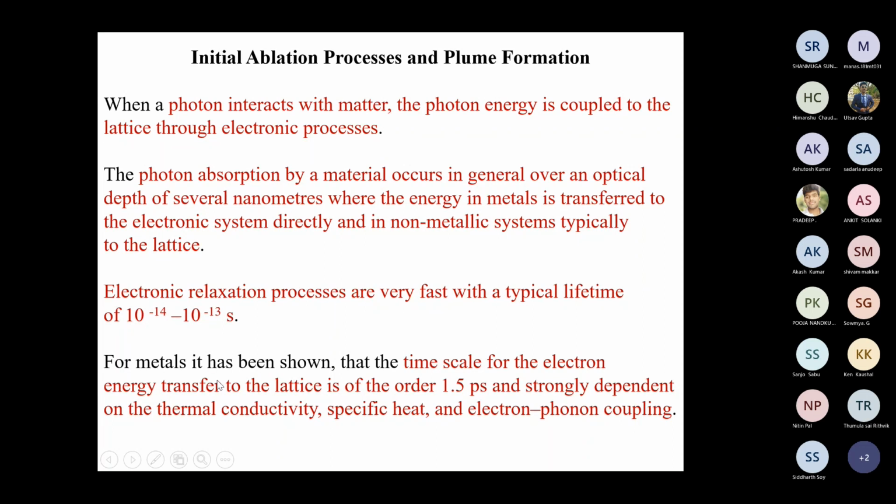For a metal, it has been shown that the time scale for electronic energy transfer to the lattice is on the order of 1.5 picoseconds, and strongly depends on thermal conductivity, specific heat, and electron-phonon coupling. So one thing is clear: whatever photon is coming needs to interact with the target material, and according to the nature of the target material, the energy transfer will happen.